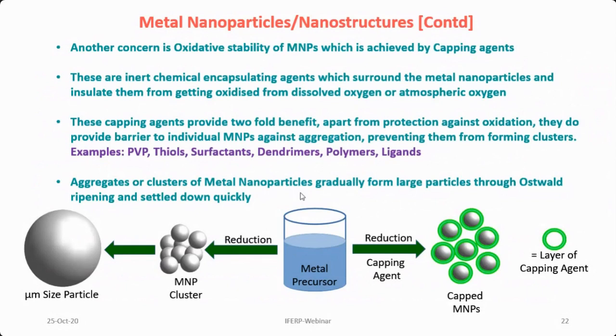So to prevent that, people use capping agents, and those capping agents are normally polymers, inert polymers mostly, like PVP and PEG, in some cases polyethylene glycols, and thiols. Particularly the gold group metals, such as platinum, gold, silver, and palladium, tend to bind with the thiol group, the SH group, and those thiols can also cover the surface very nicely and prevent oxidation as well as aggregation.